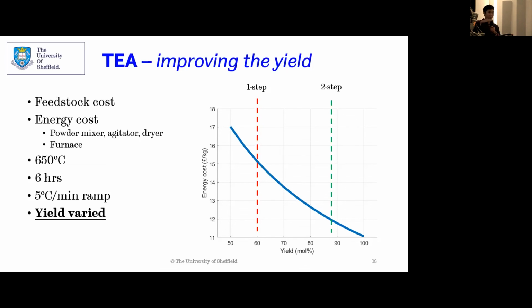So I showed you the bar graph earlier with the red, and this is how it actually looks. To put into context, the one-step reaction to the baseline, at 60% yield, costs £15. Increase the yield to 88%, and that only brings the cost down to £12. So really, there's not much more improvement we can achieve.